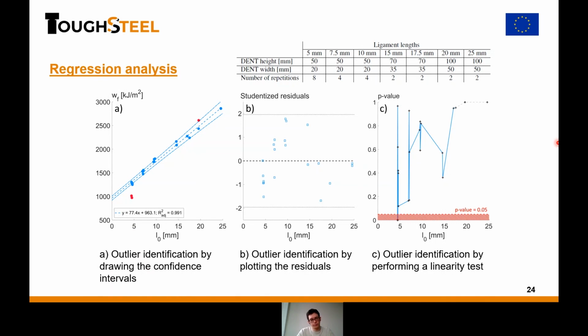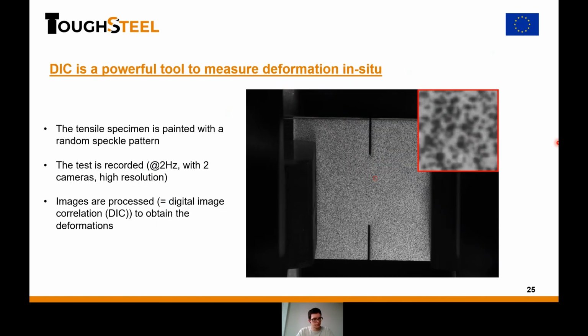Okay, so this was just for the basic linear regression methods. Next thing I would like to show you is how I use digital image correlation for my tests as well to get some extra information. So DIC, digital image correlation, is a very powerful tool to measure the deformation during the tests. So what you need to do is to have your tensile specimen painted with a speckle pattern, as you can see on the right. And you record the tests. In my case, it's 2 frames per second with 2 cameras and at high resolution. To give you an idea of the resolution, the red square here is 1 by 1 centimeter.